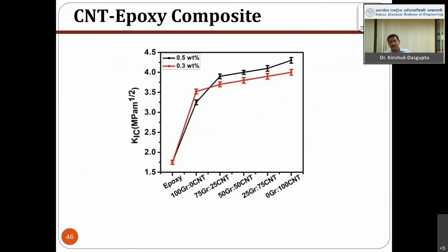And again, if we add carbon nanotube to epoxy, which is a very much used polymer, here also you can see the fracture toughness improvement is tremendous. Here we have shown, in a collaborative work with IIT Roorkee, that with epoxy, if we add 100% graphene, then 100% carbon nanotube, then a mixture of graphene and nanotube, how the fracture toughness improves. What I want to bring to your notice is that the addition of carbon nanotube, with a very small amount of addition, below 1 weight%, improves the fracture toughness tremendously, both for polymer matrix as well as ceramic matrix.